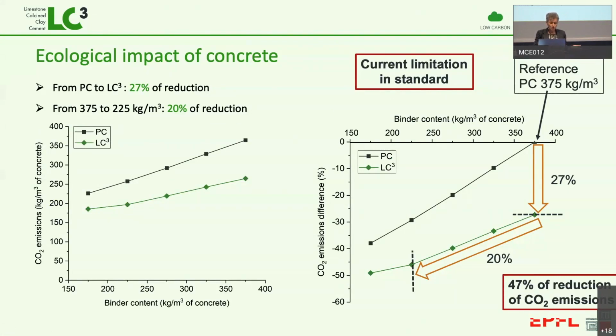Unfortunately, most norms impose a limit for the minimum cement content. Typically 300 kilos per meter cubed is the limit for most specifications in Switzerland. So we could do a lot better than we are doing, but we can't go beyond that because unfortunately these norms were put together before the days of admixtures. And so that minimum cement content is what you would need to get the correct water-cement ratio without admixtures. So here there's also work to do. So this is just a simple illustration that, as I said, things don't stop at the cement level. You have to follow through the whole value chain.